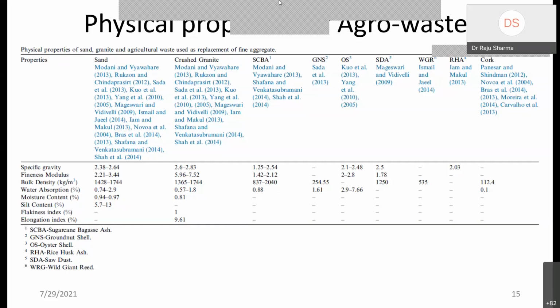So if you see the mechanical, means physical properties of these particular materials, you can see that the specific gravity is 2.38 to 2.64, and crushed granite is also having the same, but a bit higher than that because it has a dense microstructure. This granite has a denser microstructure than the sand. And then you have SCBA, right? You have sugarcane bagasse. As you can see, there is a variety in the range of this specific gravity.